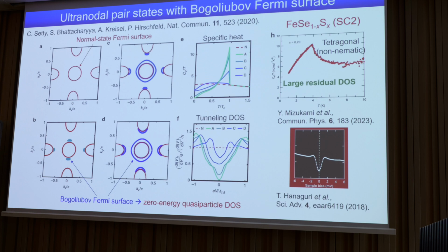Later on, the group of Taka Shibauchi considered this possibility in iron selenium-based superconductors. They assumed that time reversal symmetry is broken, and then searched a certain range of parameters, and found a parameter range in which you can create these Bogoliubov-Fermi surfaces, marked by the blue lines.